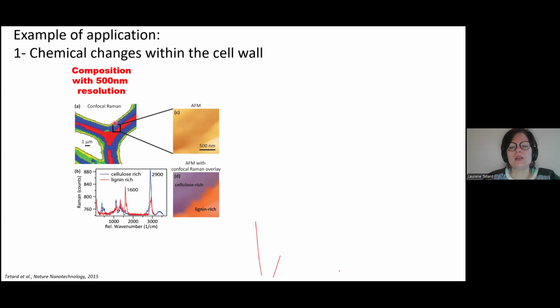And then we can image the same region with AFM, but it's a much smaller region that we image. If we overlay the topography, first of all, from the topography of the AFM, we couldn't tell whether there's a change in chemistry or not. If we look at the confocal map, we can expect that there's a region that is more cellulose rich and one that is more lignin rich. But at the time, there was no tool to confirm that.